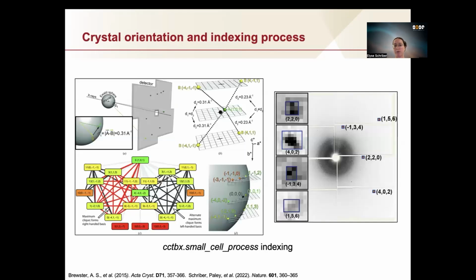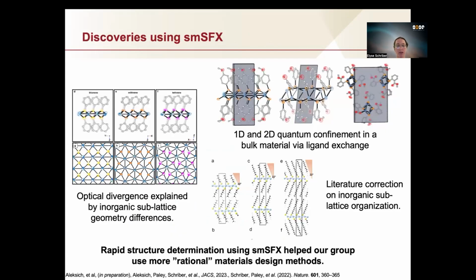Once we have a very accurate unit cell, we then are able to utilize the algorithm developed in 2014 called cctbx.small_cell_process. And the way that the small cell algorithm works is that it uses a maximum clique algorithm to find the accurate nearest neighbor of the spots that we have available. And from there, it can recreate the periodicity that's needed to find the crystal orientation. So that in combination with the unit cell parameters and the correct crystal orientation allows us to index each of the frames properly.